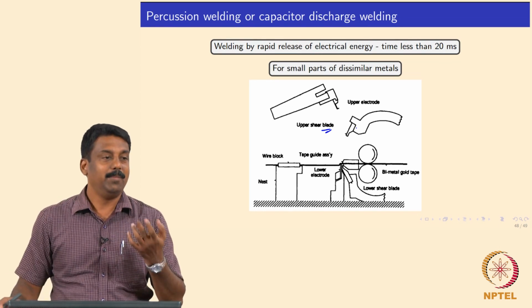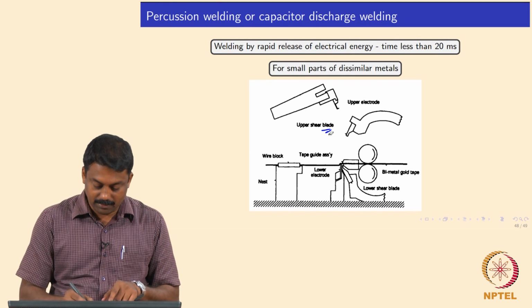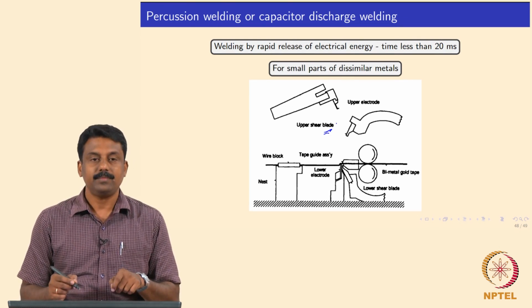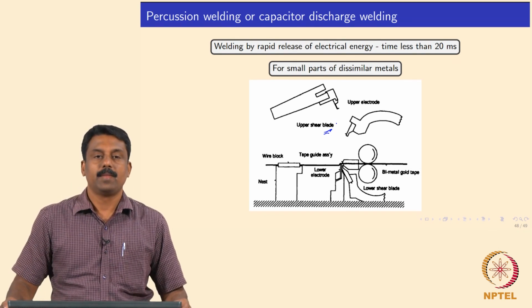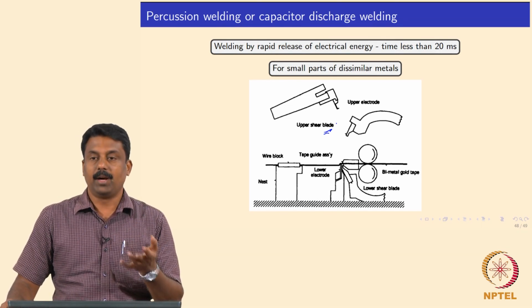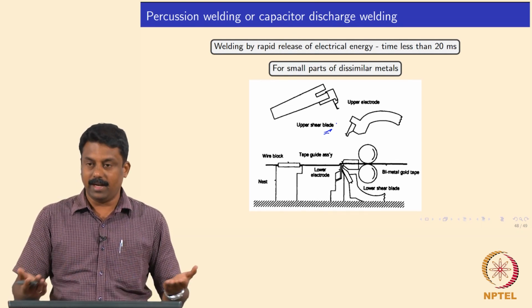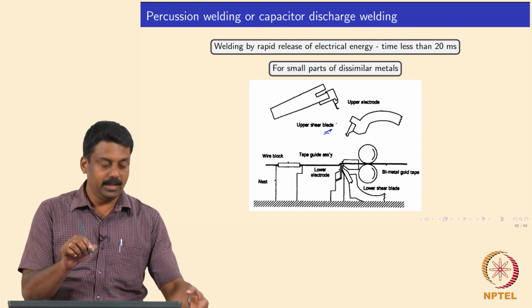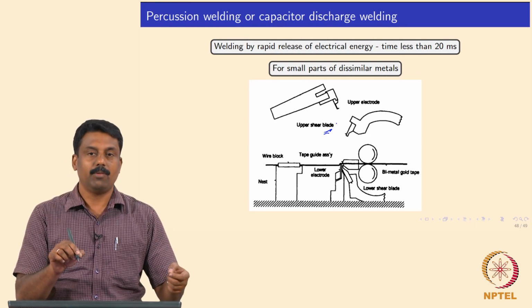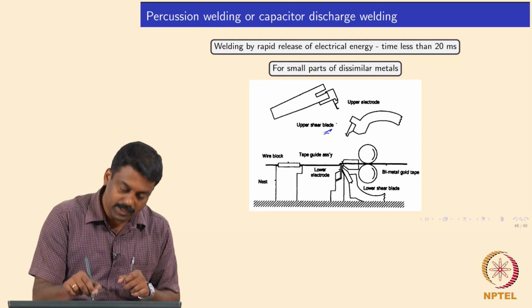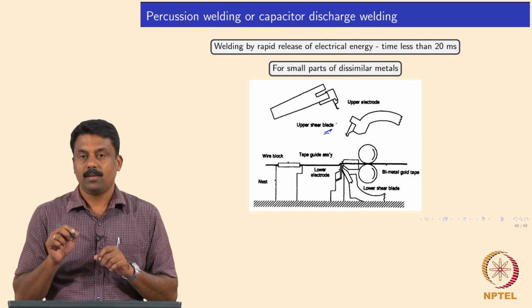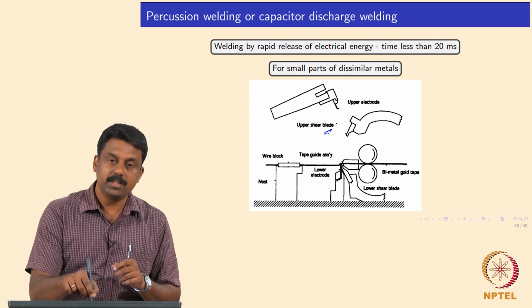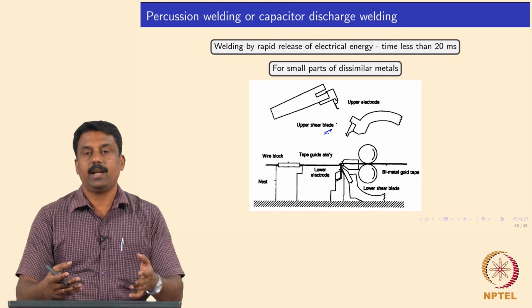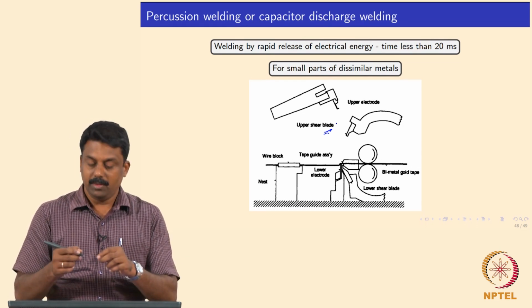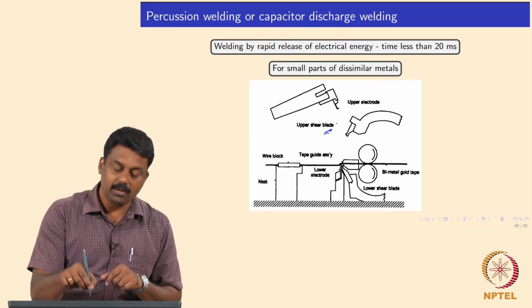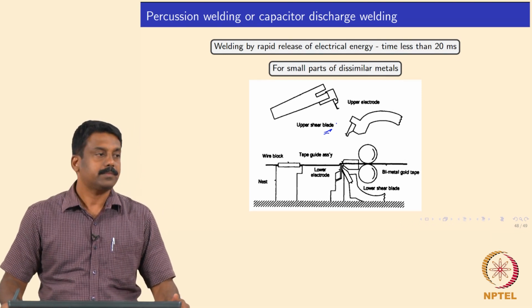Each weld would take hardly a millisecond, and one electrode would be going, for example, I have shown a schematic, the upper electrode, and then there will be a shearing blade. We have one equipment in our lab to weld thermocouples. Thermocouples are thin wires welded on a flat sheet, isn't it? So we attach a thermocouple to one electrode. The material to be used will be another electrode. We pass positive and negative ends, and then you discharge a current, and simultaneously you also apply a compressive load. The electrode is sometimes dropped on its own weight onto the sheet, and the moment you have a contact, a large amount of electric energy is discharged. In that process you end up heating the edges, and there is also a compressive load acting on the surface, leading to a weld formation, right.